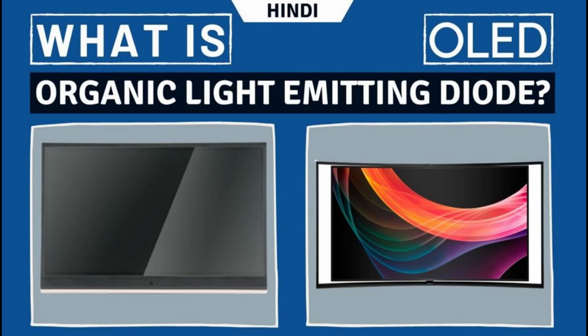Furthermore, plastic substrates are shatter-resistant, unlike the glass displays used in LCD devices. Flexible OLED displays are made on polyimide plastic films which are bonded to glass panels during production. Once the OLED display is encapsulated, a laser is used to separate the plastic from the glass in a laser lift-off, LLO, process.